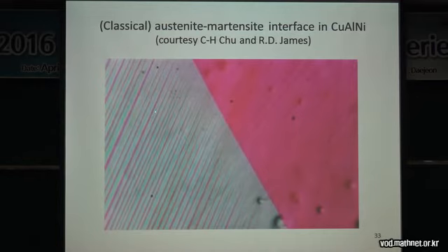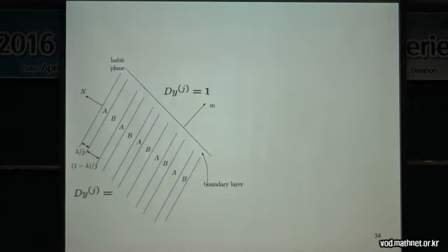So over here we've got a simple laminate of the martensite. It alternates between two values, and neither of them is rank one connected to this. So the material does the next simplest thing possible. It forms this very fine laminate, which on average is compatible with the austenite. And here you can mathematize that. You can think that you've got a sequence y_j, say a minimizing sequence, that's a simple laminate over here, alternating between A and B. So A and B would be twins sitting on the different energy wells. And over here is the identity. But there has to be some kind of interpolation layer because A and B are not compatible with the identity.